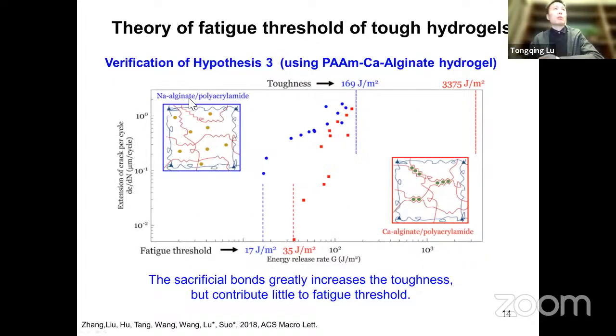So the result is as I predicted. The horizontal axis is still the energy release rate, and the vertical axis is the extension of crack per cycle. There are two numbers: one is toughness, the other is fatigue threshold. The red one is the tough hydrogel, and the blue one is the ordinary hydrogel. We can see the toughness of the double network hydrogel is almost 20 times the toughness of the ordinary hydrogel, but the fatigue threshold differs by only 2 times. So it's as I predicted: the sacrificial bonds greatly increase the toughness, but contribute little to the fatigue threshold.